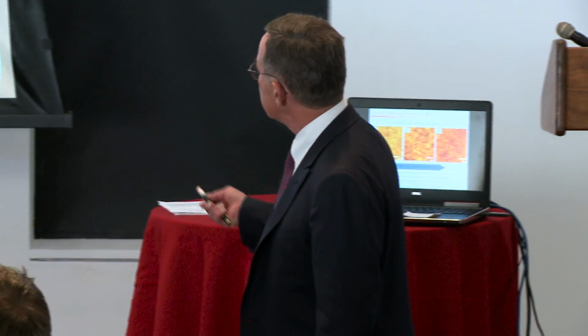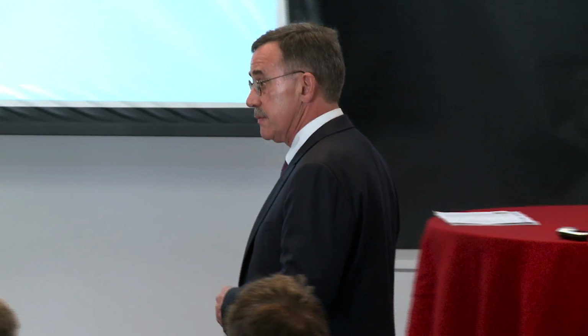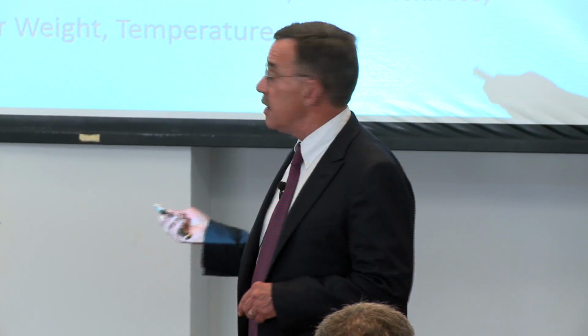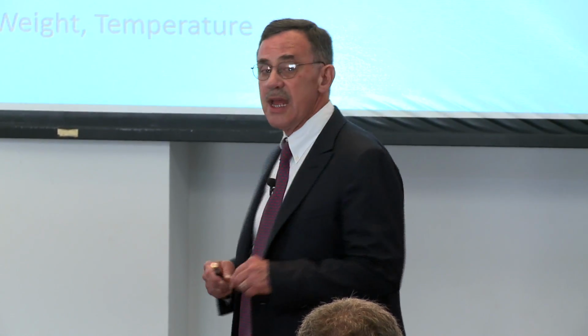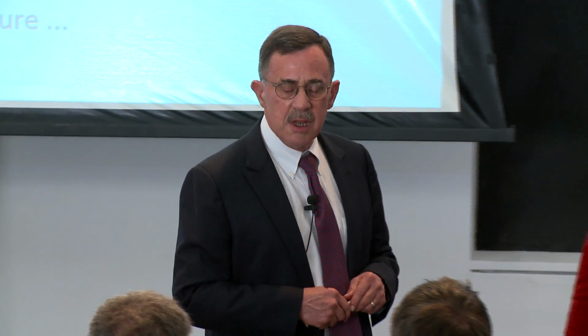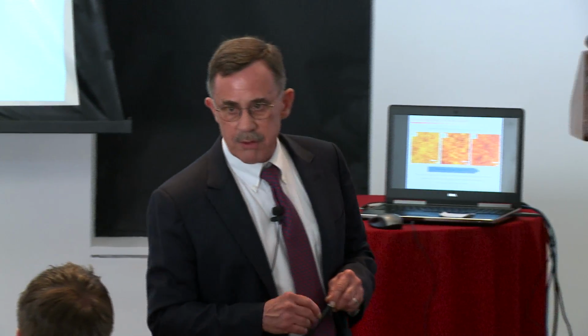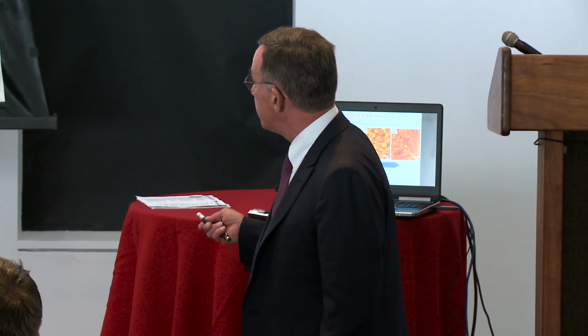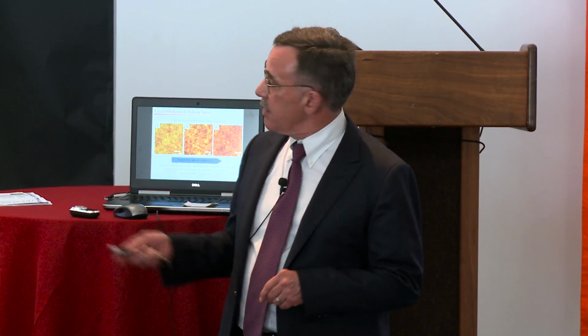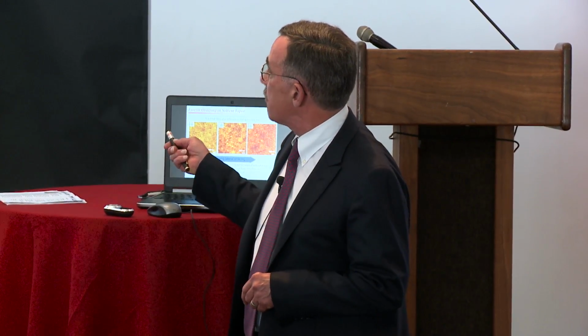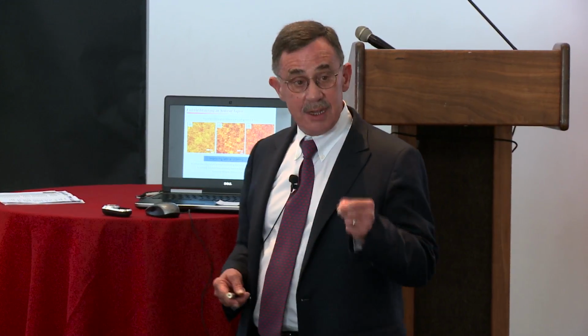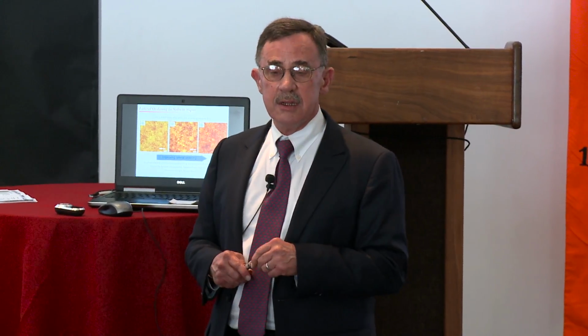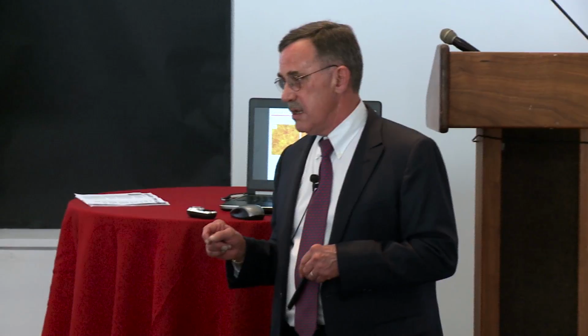And in fact, you start generating these structures where you see this beautiful hexagonal array of cylinders. It's really nice. And in this particular case, the question is, can we take these films and control the ordering, the lateral ordering? Because if I could address each and every one of those elements, if I could sit on a cylinder here and go over a certain amount to another side and tell you whether I'm on a cylinder or not, that means I can address it. And if I can address it, that's storage.